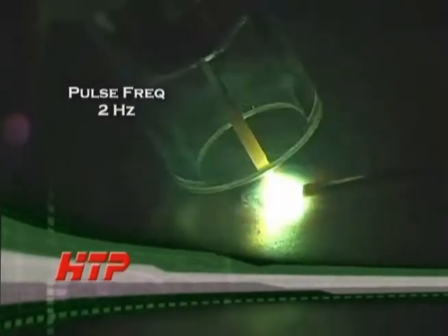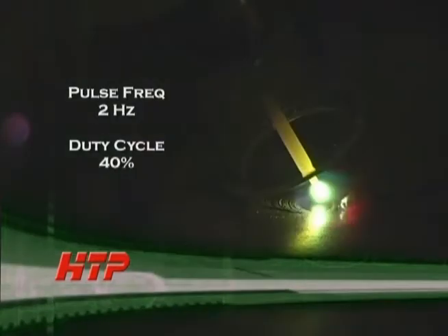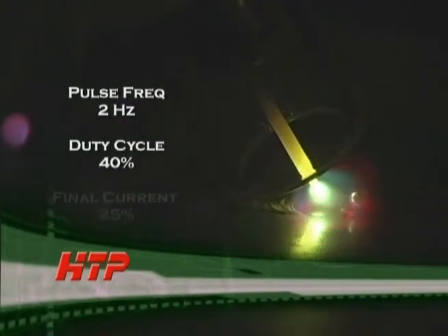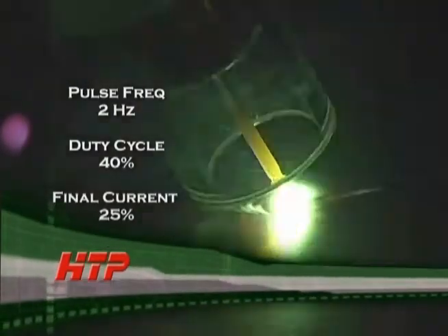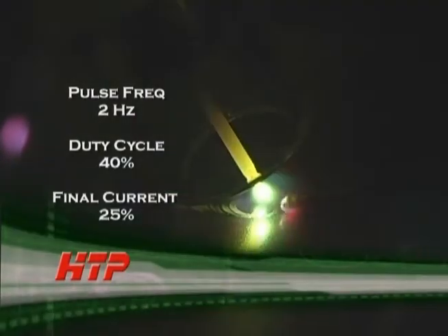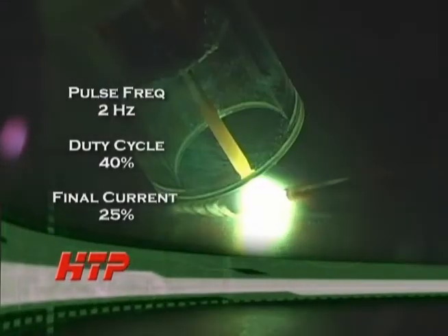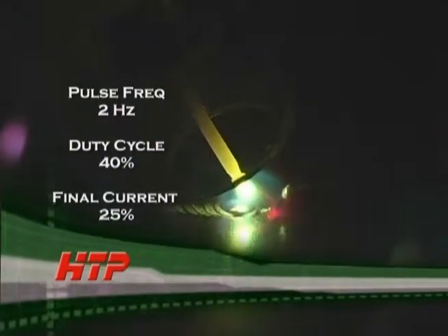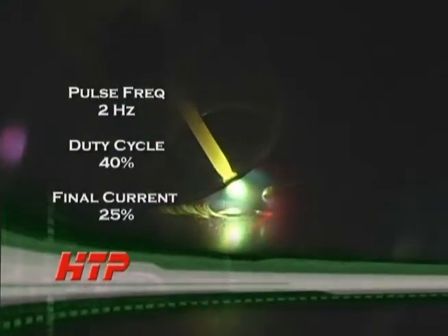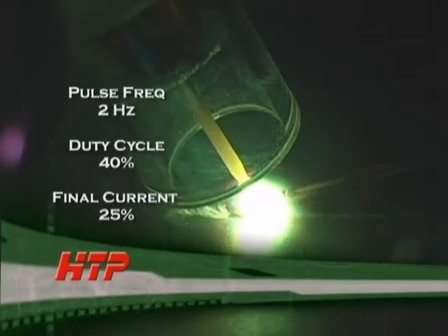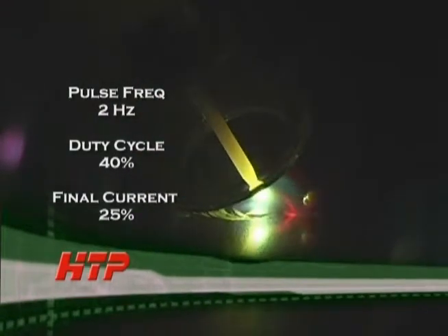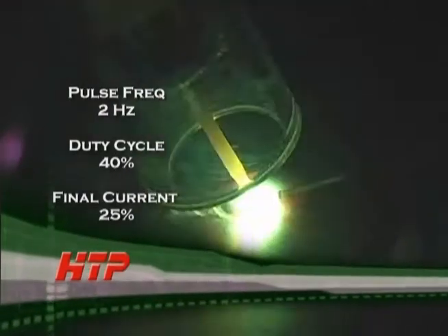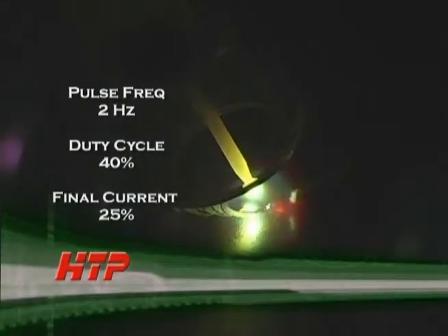First, we are going to show you a slow speed pulse. We are set at 2 Hz or 2 pulses per second, a duty cycle of 40%, and a final current of 25%. A slow speed pulse can be used to help you time dabbing the filler metal. You can see we are dabbing the filler metal every time the machine pulses. It is important to note that you never want the duty cycle or the background current set so low that the molten puddle will completely solidify, as this may cause cracking.